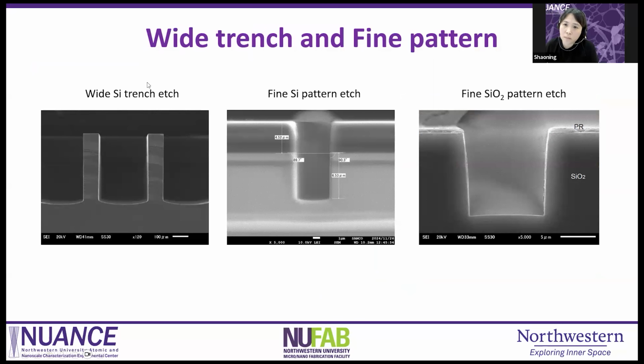So these are examples of what we can etch in this machine. You can see this is a wide silicon trench etch. The width of this trench is 300 micrometers, and the depth is over 300, actually nearly 400. And this is a smaller trench, about 5 micrometers wide, 10 micrometers deep.